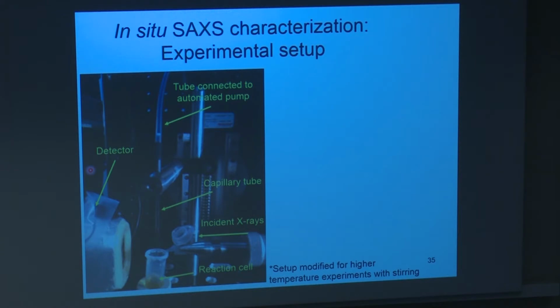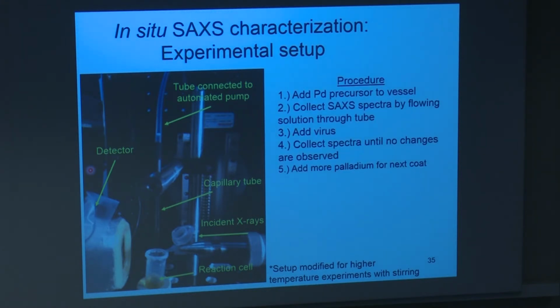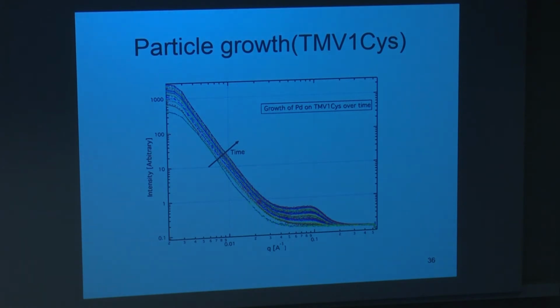Now, we also want to look at the particles that are growing on the surface of the TMV. And so we use small angle X-ray scattering. As you can see, I'm going back to small angle X-ray scattering over and over again. I started with it in the first set of experiments I did before coming to Purdue, even when I was at Oak Ridge National Laboratory. And also using some type of spectroscopic technique in order to monitor the reaction kinetics of the material. So, here we use small angle X-ray scattering, where we have a quartz tube, and then incident radiation goes through the tube, sampled in the tube, and you get scattering, and you get a scattering pattern that looks something like this, and you see it varies as a function of time,